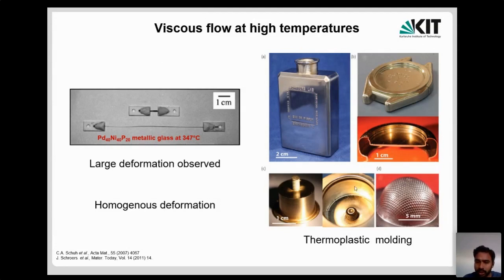this is thermoplastic molding, where you take a glass and then you heat it to high temperature. And at this temperature, the glass is sort of like a viscous liquid, and you can just press the glass into different shapes. Like the one here, you can make a bowl kind of shape. And this is very, very fascinating to understand. And one of the reasons is that there are no catastrophic shear bands, and the material is sort of like a viscous liquid. So it's sort of like a homogeneous deformation. Okay. So it's a very important application of metallic glasses.